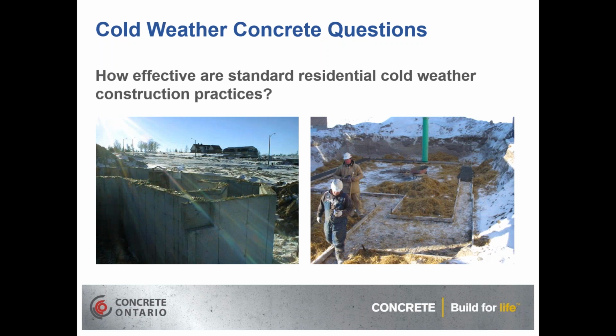The concern with residential walls is that when it comes time to backfilling the wall, if the concrete element hasn't reached sufficient strength, there's potential for structural cracking from the backfill operation. So you want to make sure that when you're doing residential walls, that you are protecting the concrete, you're ordering the right mix, and that it's giving you the appropriate strength and durability to be able to strip and withstand freezing and thawing cycles.